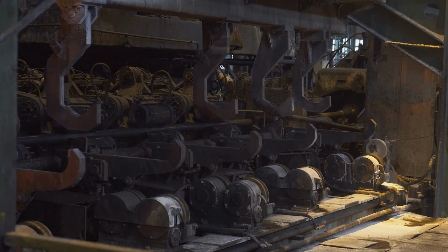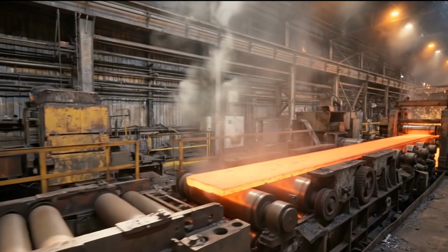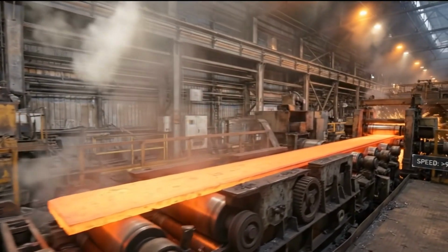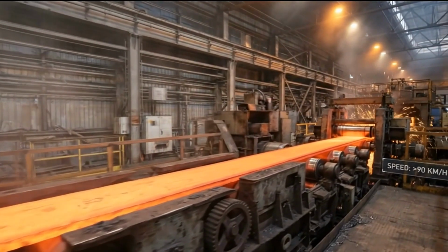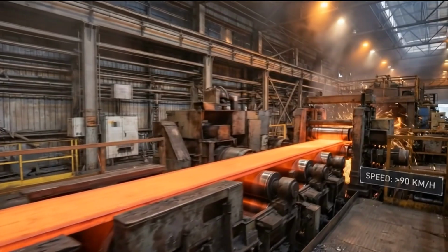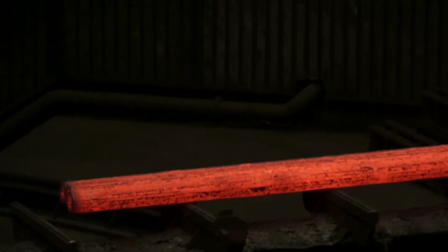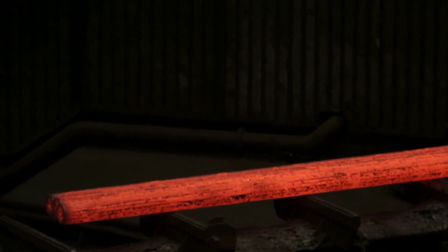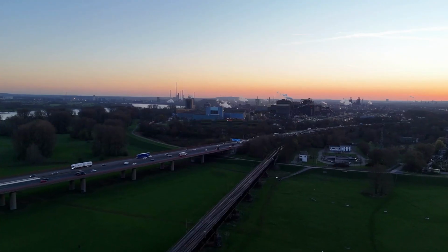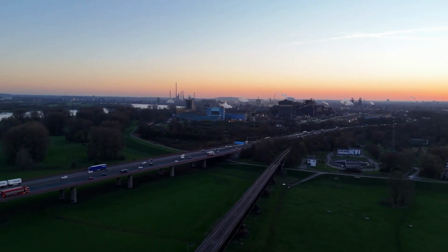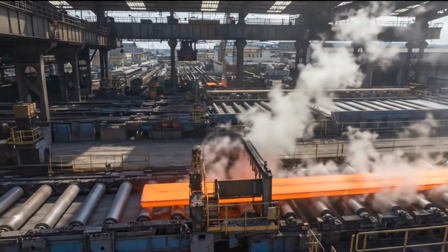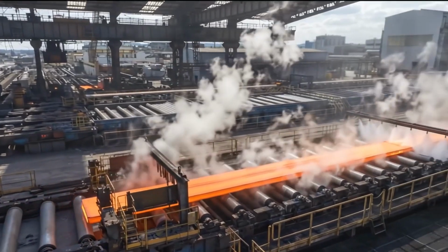Then it enters the finishing mill, a continuous tandem arrangement of typically 6 or 7 stands, each one reducing the strip's thickness by a controlled percentage, the strip accelerating as it gets thinner because the same volume of metal has to move faster to maintain continuity through the line. By the final finishing stand, the strip is moving at speeds that can exceed 90 kilometers per hour. A strip of steel, glowing orange, thinner than a fingernail at the thinner gauges, traveling at motorway speed across a runout table 300 meters long before it hits the coiler.